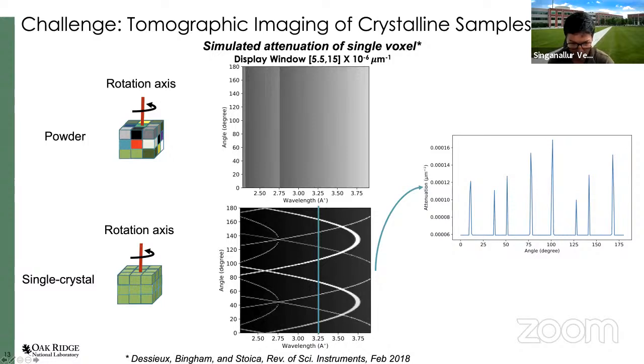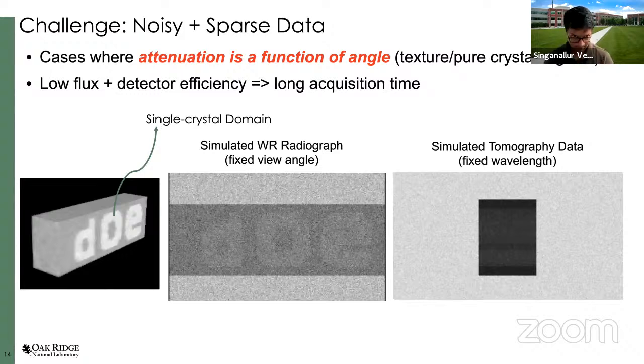So what you're looking at in this picture, for example, is the attenuation coefficient as a function of angle and wavelength for a pure crystal. And you can see that as the crystal is rotated, if you fix a certain wavelength, at certain angles you're going to get a sharp spike in the attenuation in the transmission direction, because the beam diffracts strongly. So this makes it very challenging to do CT because the attenuation is essentially changing as a function of the rotation angle. But the nice thing is this can be sparse. That is, it only changes at a few locations, which we can exploit when we try to build algorithms for such cases. So that is one of the challenges, that you can have an attenuation which is a function of angle.